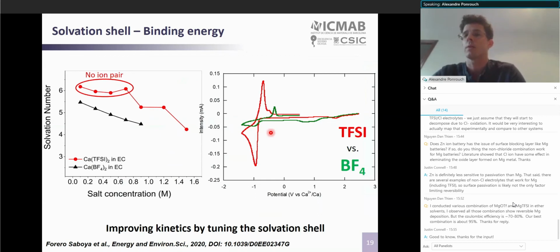And if we look at the Raman spectroscopy results, here what we can observe is the fact that in the calcium TFSI based electrolytes, and for the concentration we are working at, which is here 0.45 molar, we do not have the formation of any contact ion pair, or at least not detectable from Raman spectroscopy. While in the case of calcium BF4 based electrolyte, we already have a significant amount of contact ion pair being formed in this electrolyte.